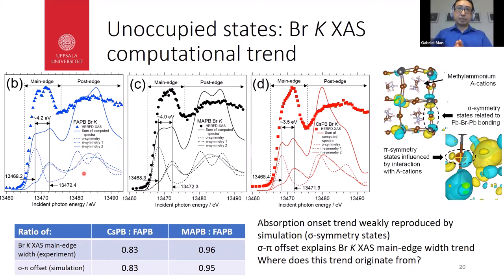Now I'm going to show you a comparison between the simulated and experimental spectra for the three compounds. The experimental spectra are shown in markers, and the aggregate simulated spectrum is the solid line. Then there is the decomposition of the simulated spectrum into its components, which are primarily two: the sigma symmetry states and the pi symmetry states. In the diagram, the sigma symmetry states are related to lead-bromine-lead bonding, and the pi symmetry states are orthogonal to this, so they could be influenced by the A-cation.